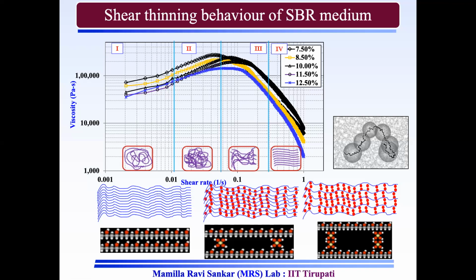It is reducing because of low molecular weight materials, that is plasticizers. You can see at the bottom in the initial stage, these blue lines which are non-linear lines are nothing but my polymer molecular chains. When I am mixing or blending with low molecular weight materials like plasticizers, what will happen? Low molecular weight materials try to go between or penetrate between high molecular weight polymer chains and try to kick them apart. So the interpolymer molecular distance will increase and interpolymer molecular strength will decrease.